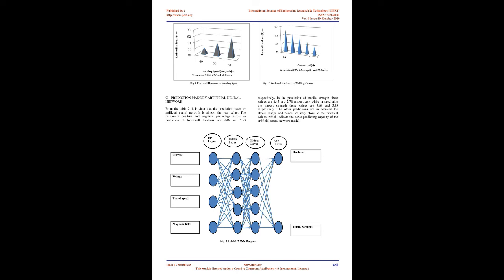C. Prediction made by artificial neural network. From Table 2, it is clear that the prediction made by the artificial neural network is almost the real value. The maximum positive and negative percentage errors in prediction of Rockwell hardness are 8.46 and 5.53 respectively. In the prediction of tensile strength, these values are 8.45 and 2.78 respectively, while in predicting the impact strength, these values are 3.68 and 3.43 respectively. The other predictions are in between the above ranges and hence are very close to the practical values, which indicate the super predicting capacity of the artificial neural network model.